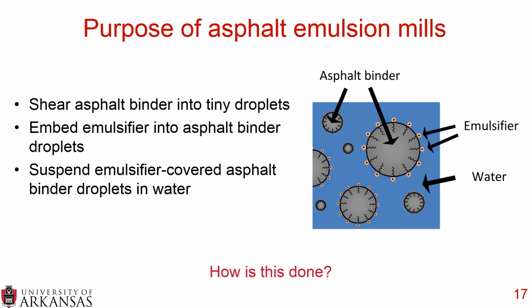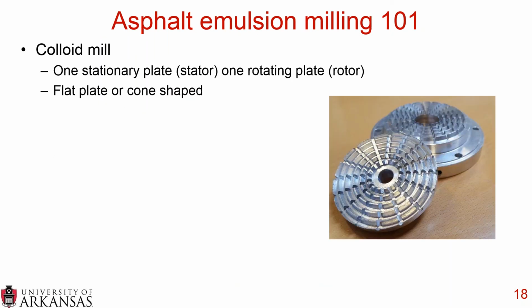Well, how do we do this in the asphalt emulsion mill? The most common type of mill is a colloid mill, and that has one stationary plate. So the picture on the right, that's the upper right hand plate. That is stationary, it's not moving, and it's called the stator. And then you also have one rotating plate, that's the one in the foreground in that picture, and that's called a rotor. And that rotor rotates and it shears asphalt binder into droplets. So the material comes in through that hole in the center and it gets forced out, it gets sheared between those two plates, and you get your asphalt emulsion.